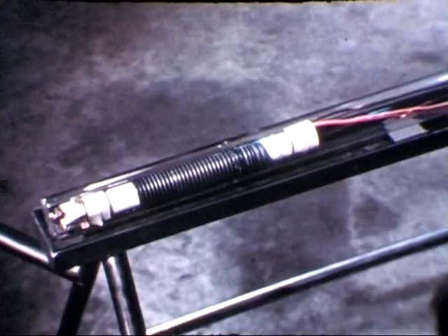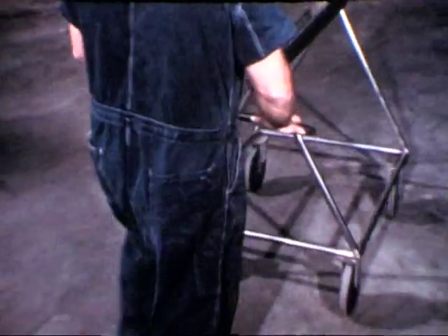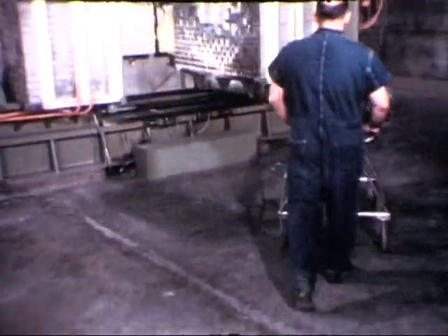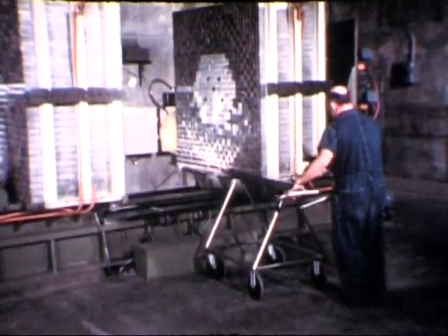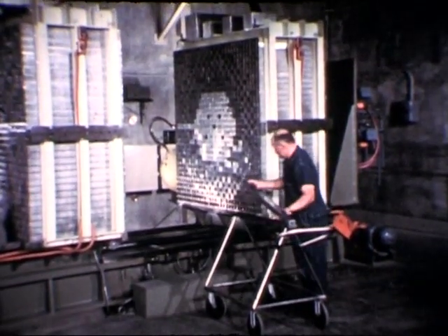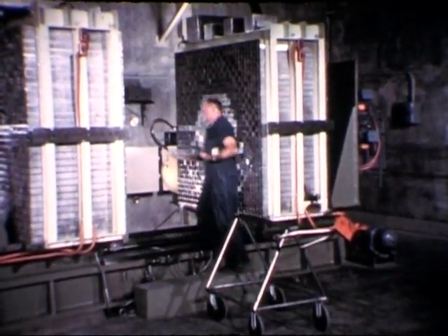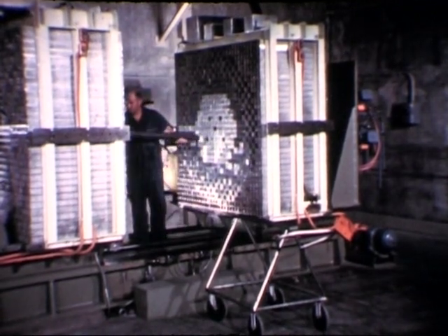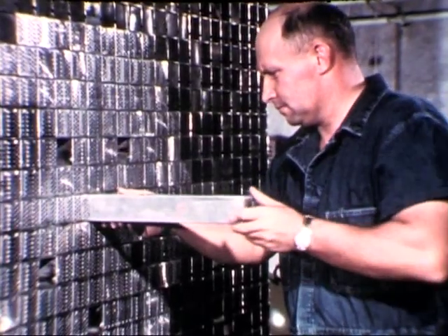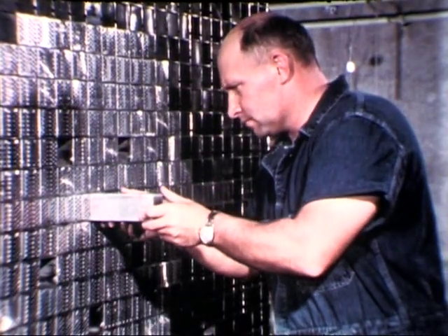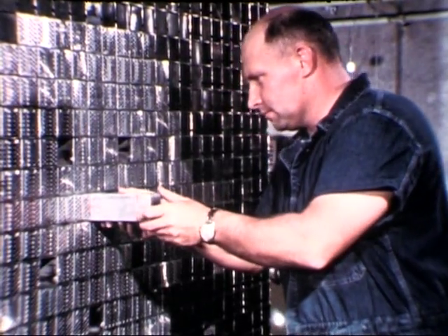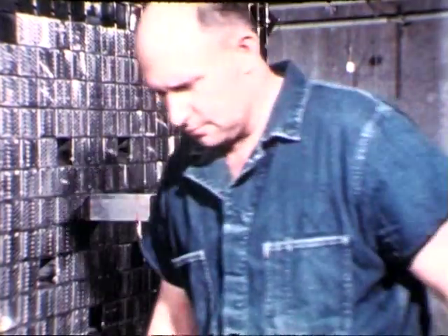Enriched uranium in the form of a helix was prepared for measurement of the Doppler effect in fast reactors. This experiment was performed in the laboratory's critical assembly facility, ZPR-3. The helical form was adopted to minimize motion due to heating, which could produce undesirable side reactivity effects. Positioned within an assembled EBR-1 core mock-up, the helix was periodically heated, then cooled on a 20-second cycle time.